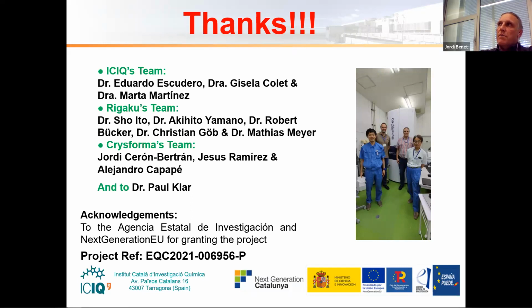But there is one point which is important for me. It's a time-demanding method, because when I do single crystal with the X-rays, I go there, mount the crystal, go for a coffee, then I look for the cell and I refine the structure. So it's a time routine which allows me to do it. When I am sitting on the ED system, it's like hell. I measure crystal after crystal. I get a lot of data sets. I have to process all these data sets. I have to see which is the correct one, which are the correct cells, which ones I can merge, so that you cannot go. I spend hours and hours in the lab and look at the clock.